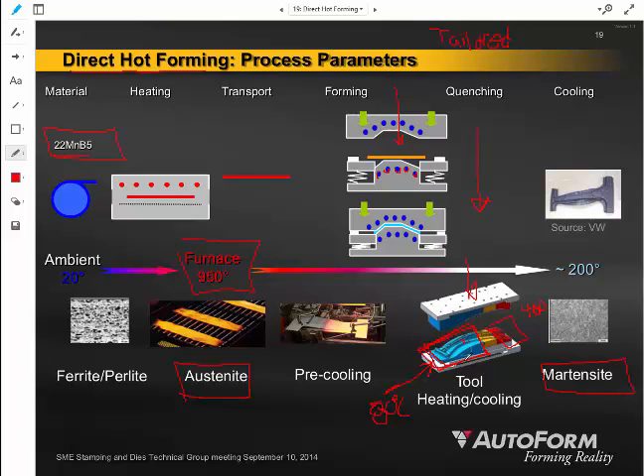So if I quench just the top part of this B pillar at 80 degrees C and I held the lower part of the die at 400 degrees Celsius, what will happen is that the lower part of the B pillar would not form this martensite. It would form more ferrite, more bainite in its microstructure, and therefore it would not have the super strong 1000 megapascal finished yield strength. It would finish up in strength more like what the material's original strength was when we received it from the steel mill. This material at the top, where we're quenching it to that 80 degrees C using this very cool tool, that's going to form a higher degree of this martensite, and that top of the B pillar would presumably be all at this martensitic microstructure and achieving that 1000 megapascal yield strength.